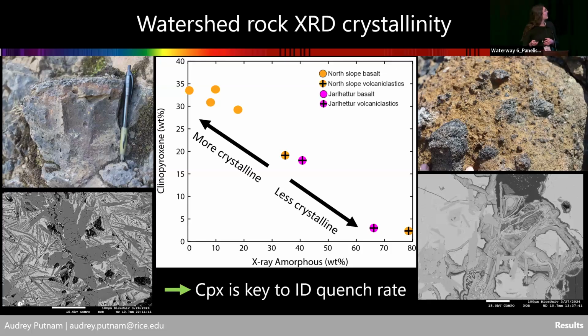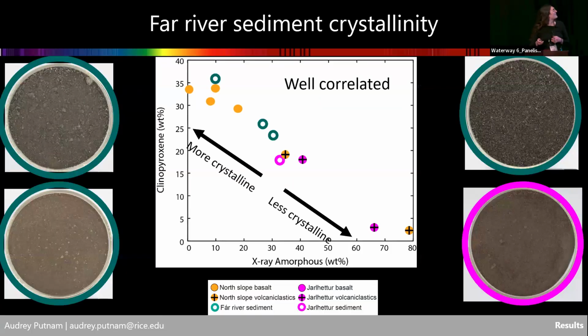So now let's overlay some of our sediment samples taken from, again, the coarse-grained river sediments in that river and delta. And what we can see, those are the open circles, by the way, is that they follow this trend very nicely. We don't see any evidence for additional amorphous material being added to these particular sediments, and that makes sense here. We can also see that they are showing a large variation in the weight % of clinopyroxene that is telling us about overall crystallinity. So it's varying between about 20 to 35 weight % clinopyroxene.